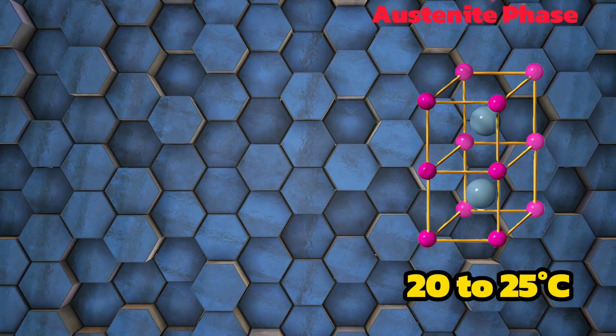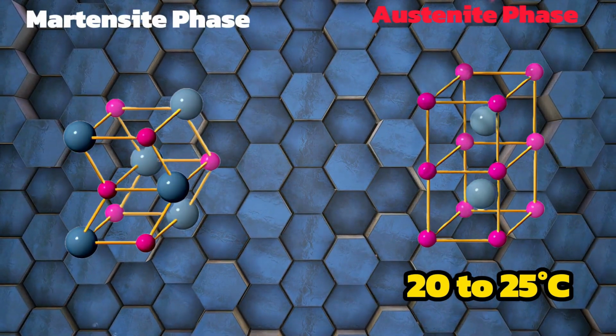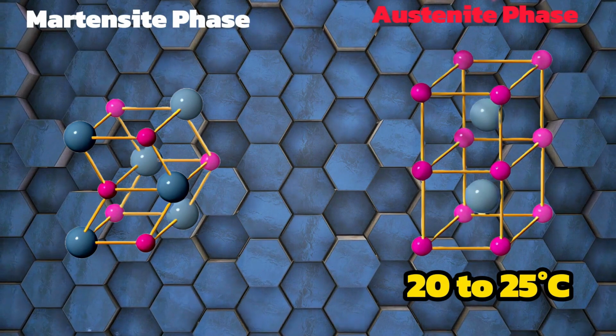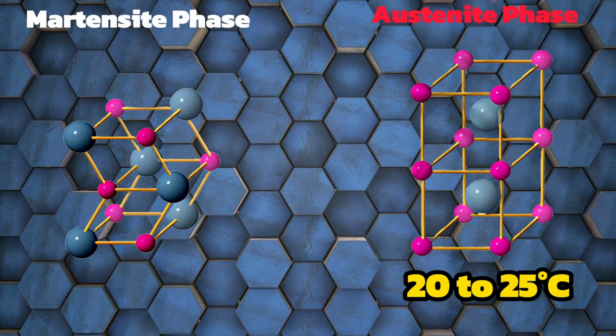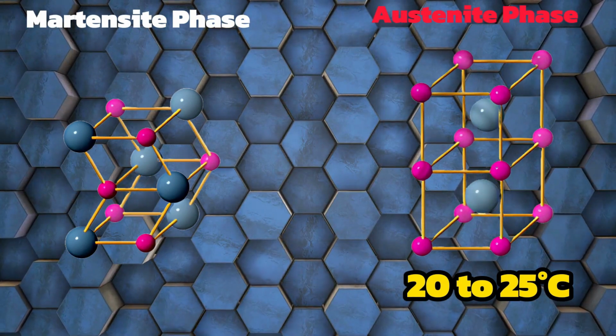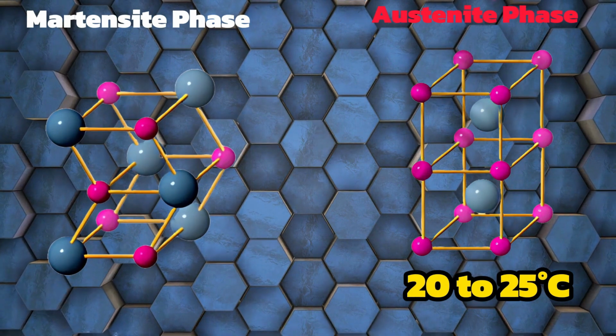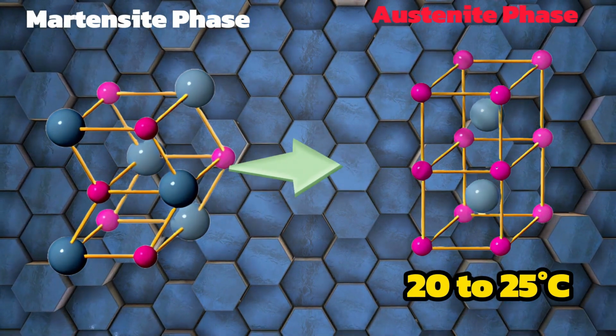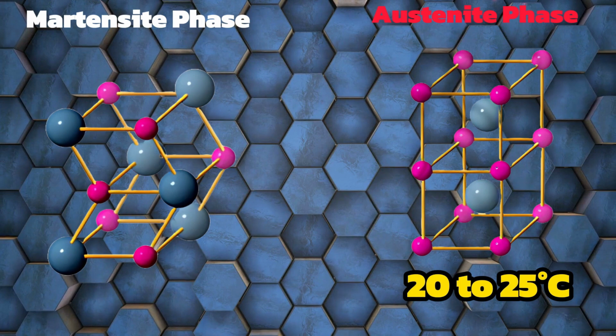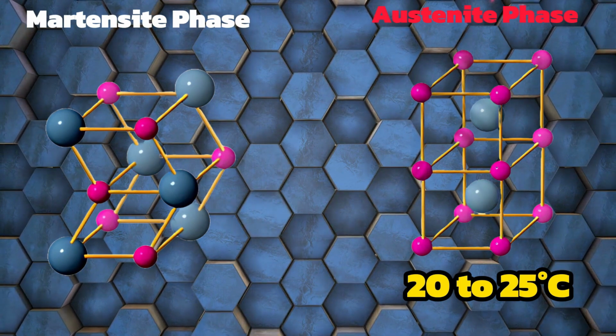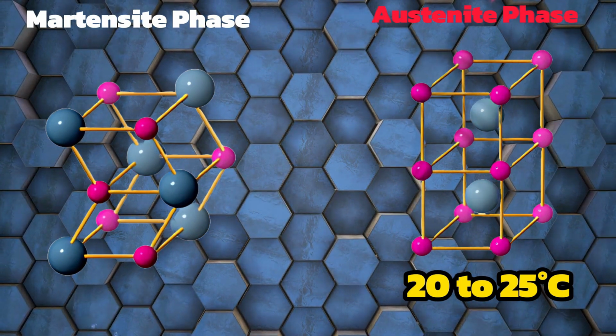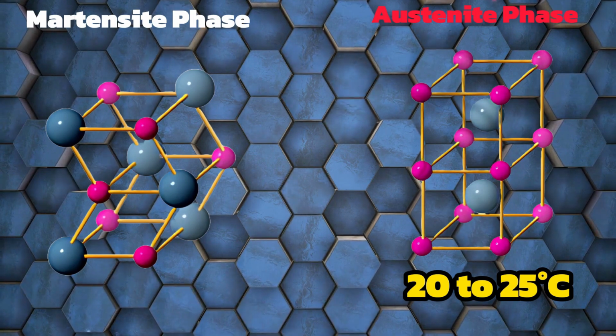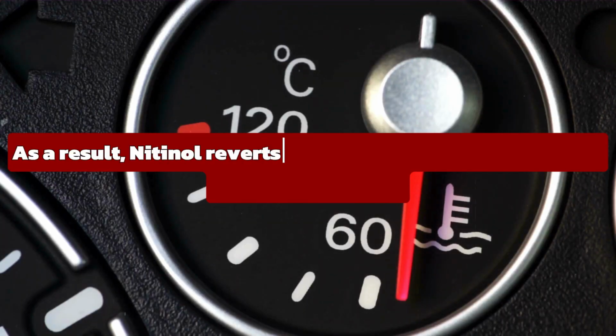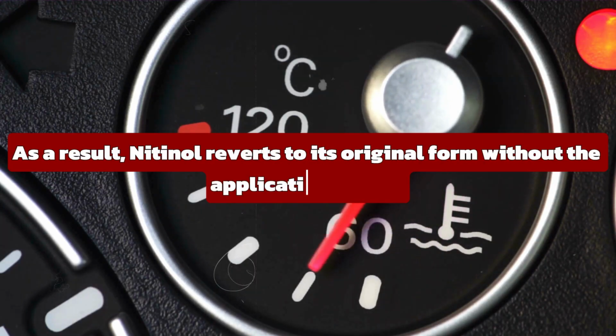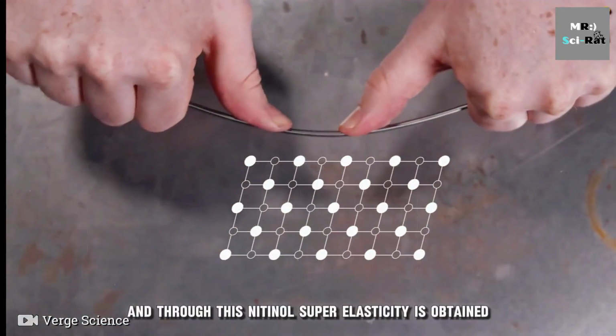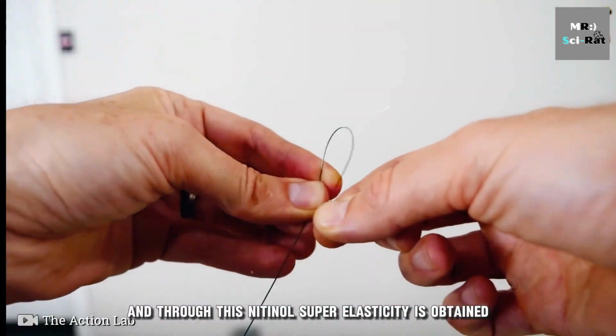As a result, nitinol is deformed to the martensite phase and then it goes to the austenite phase even if no temperature is applied separately, because the temperature set for the austenite phase is 20 to 25 degrees Celsius. As a result, nitinol reverts to its original form without the application of heat. And through this, nitinol superelasticity is obtained.